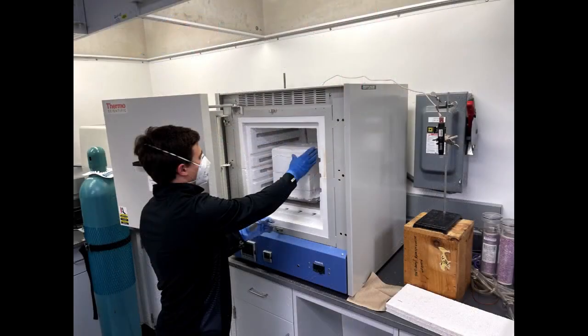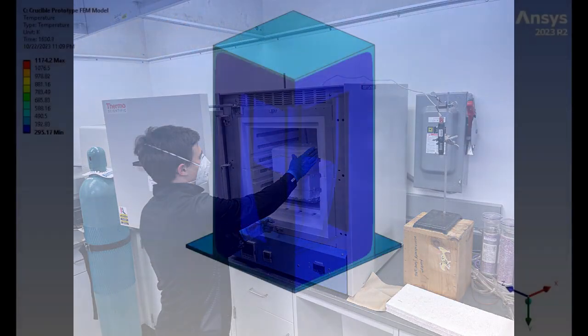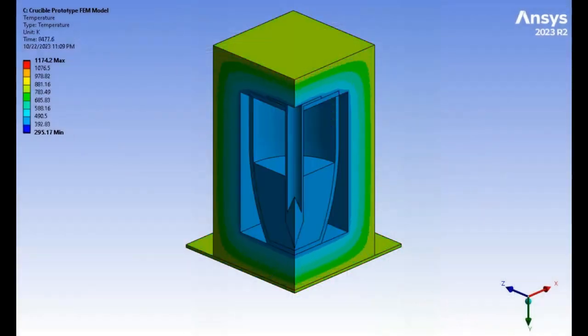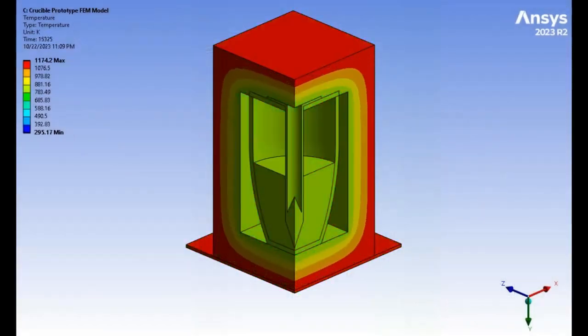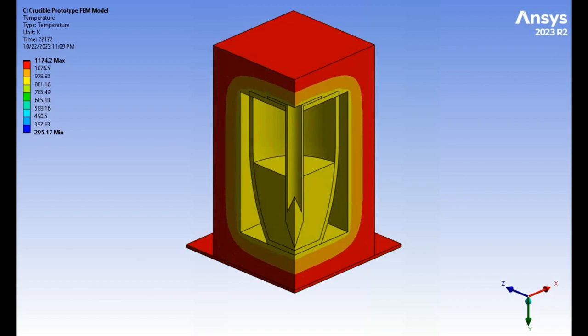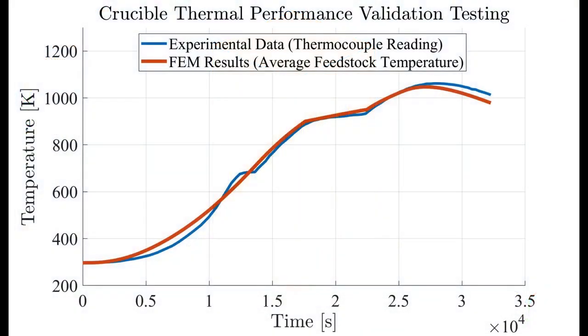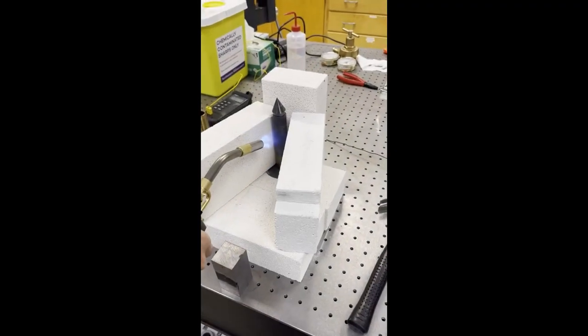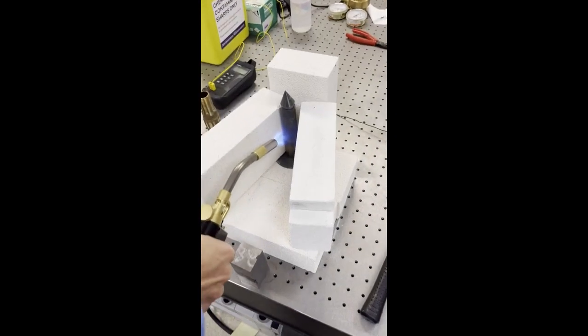The experimental data was compared to a transient thermal simulation with boundary conditions set by the controlled external temperature. The feedstock temperatures predicted by the model closely aligned with the experimental data, with an average magnitude percent error of less than 2.5%, validating the insulative properties of the crucible as well as the team's ability to accurately simulate its thermal performance. To assess the performance of the tungsten probe, the team completed a ray tracing study in ANSYS SPEOS.